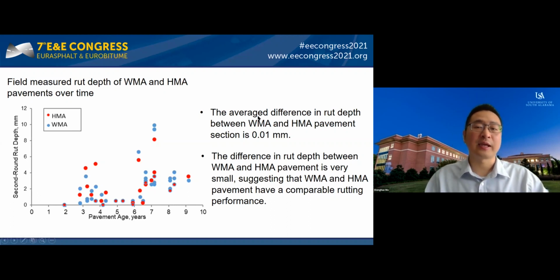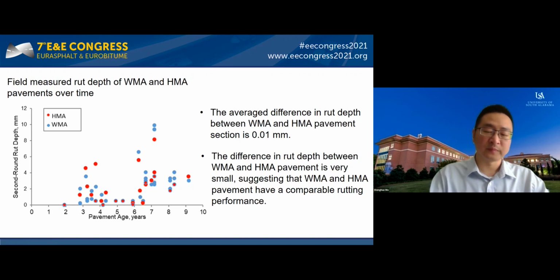So for the rut depth measurement, as you know, HMA and WMA are showing very low rut depth. If you calculate the difference between the HMA and WMA pavement sections, it is a very low number, as small as 0.01 millimeter. And this is indicating that HMA and WMA sections have very comparable rutting performance.